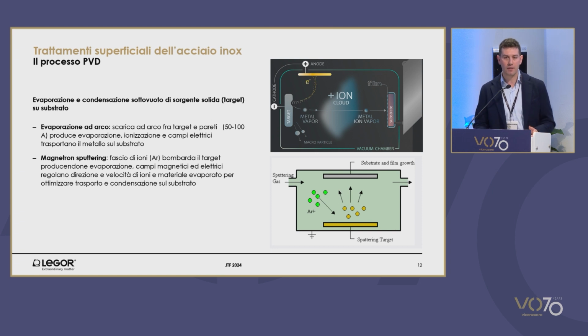An arc discharge is triggered between the target and the walls of the deposition chamber. The discharge, with a current of the order of 50 or 100 amperes, is localized over a limited region of the target surface. Sputtering can also be used. A high-energy ion beam bombards the target, detaching atoms or molecules that move into the chamber and condense on the substrate. Both technologies include the transport and recondensation of the vapors emitted by the target.